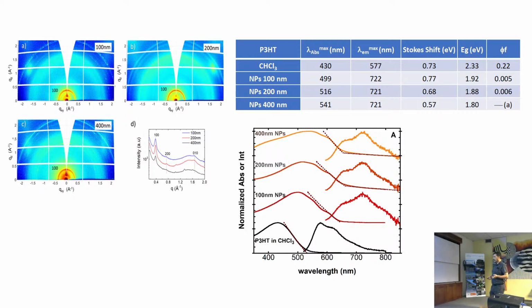In terms of spectroscopy, what we have here is the absorption spectra of the polymer in chloroform. And it is a good solvent, okay? So you have a neat pi-pi transition in here, and then you have the fluorescence, which is quite high. It has a very high fluorescence quantum yield in chloroform. But as soon as you do the nanoparticles, you start to form aggregates. And the aggregates appear as these shoulders in here, which technically are called the J aggregates.